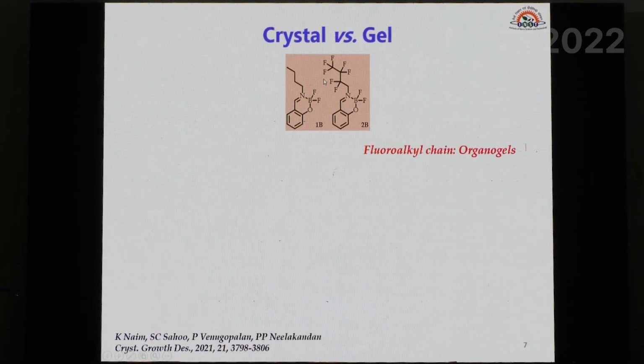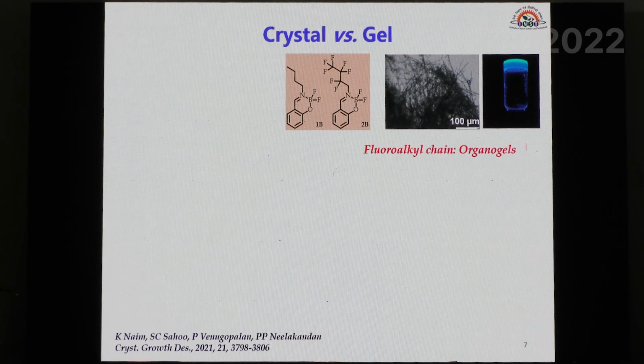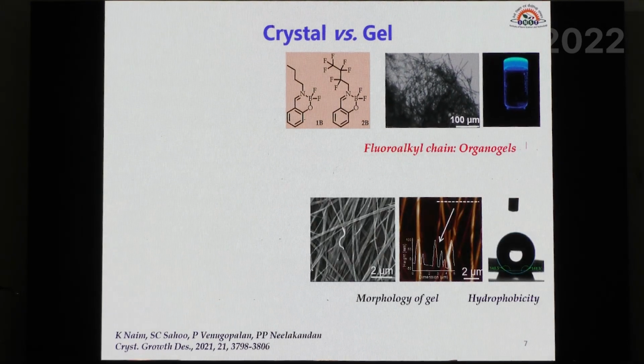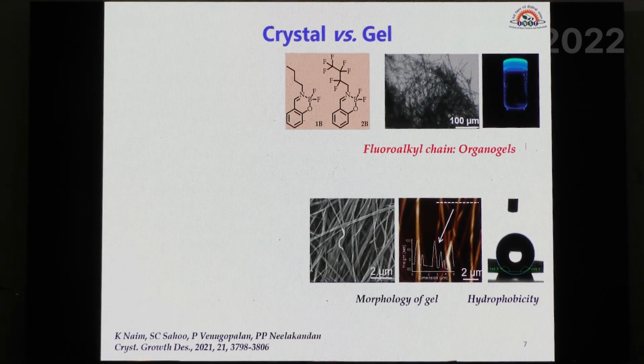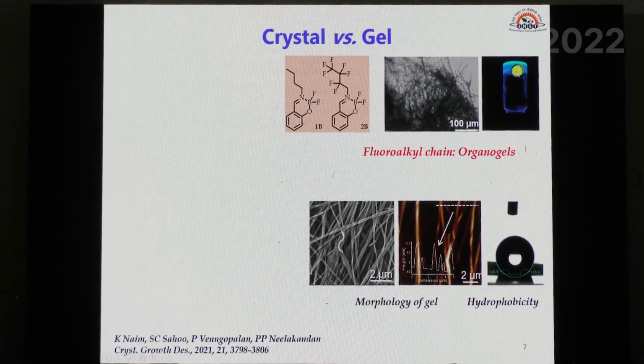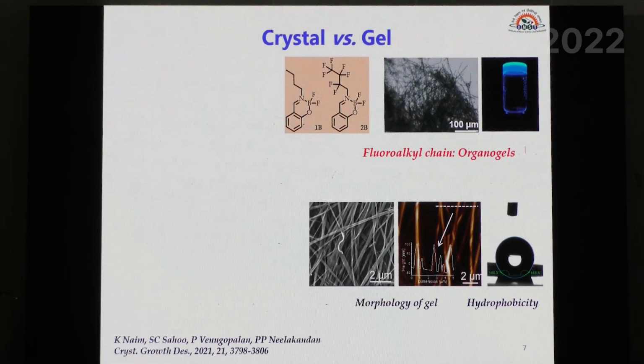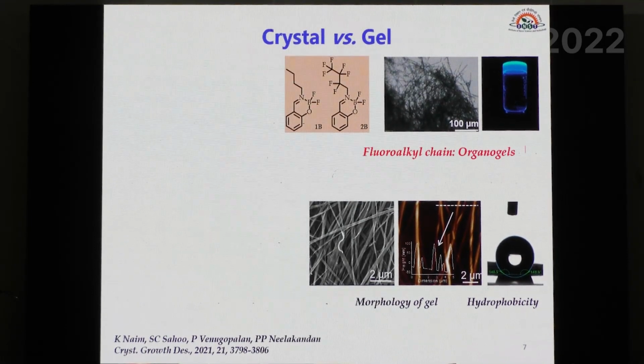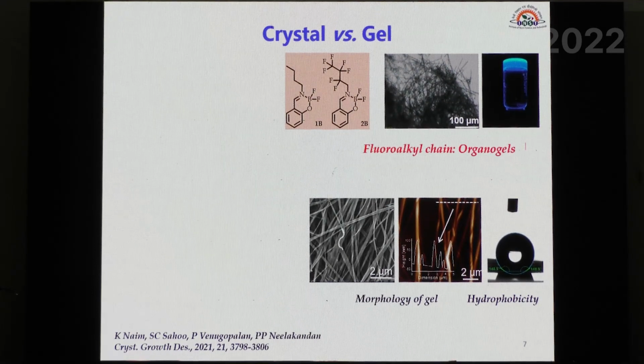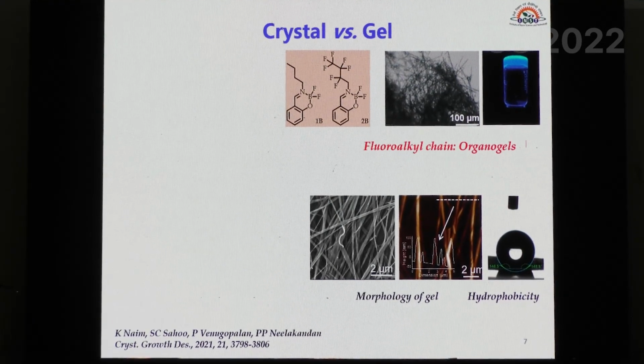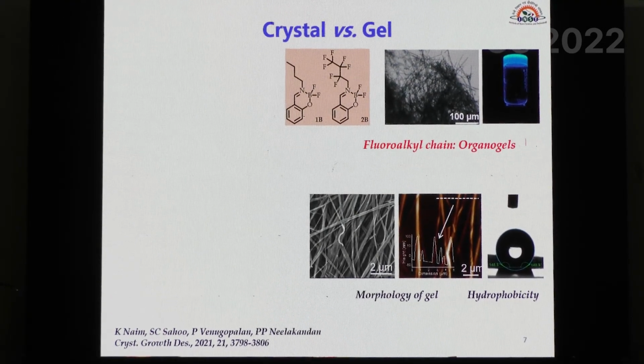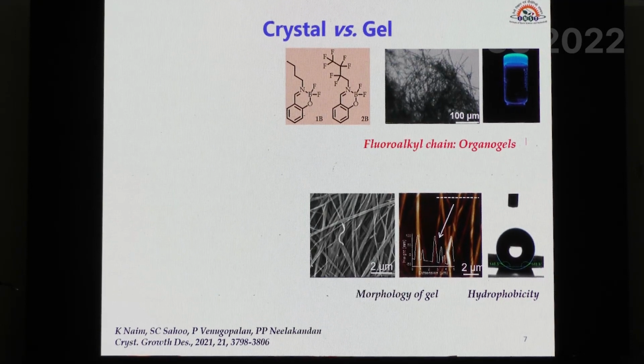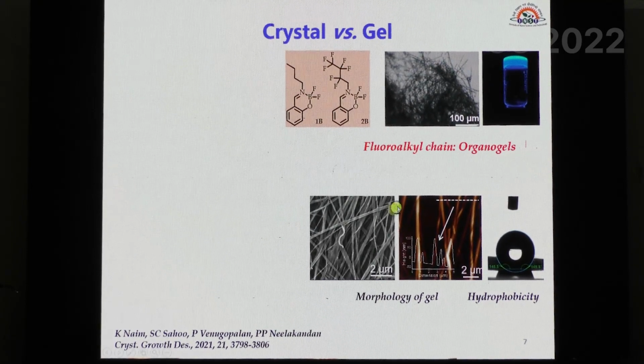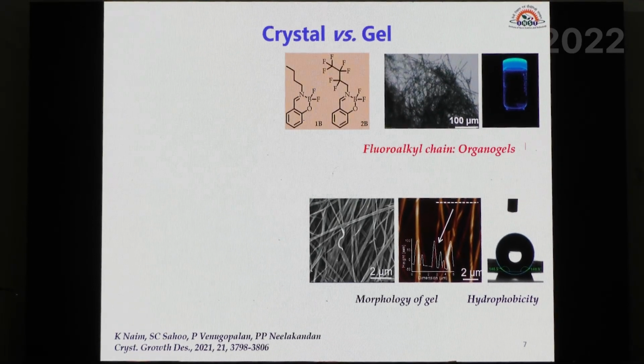When you have the fluoroalkyl chains, they did not form any crystals, rather they formed organogels. That means they hold the solvent and form gels. Having these fluoride units in it helps to increase the hydrophobicity of these compounds, and they were found to be highly hydrophobic and very close to superhydrophobic in nature. They have linear, fiber-like structures when we analyze them through various microscopic techniques.